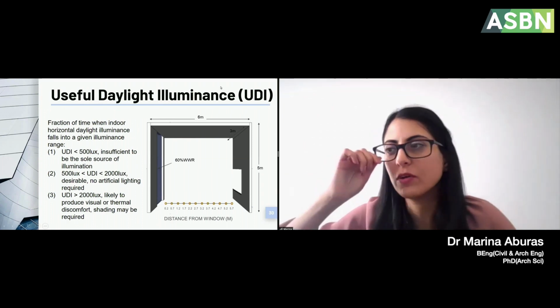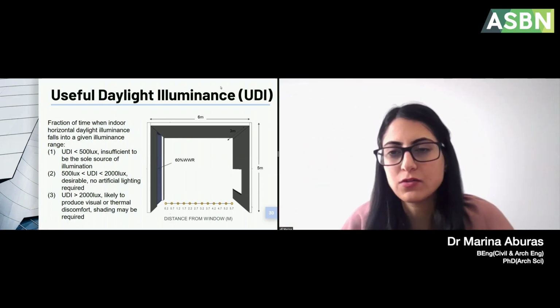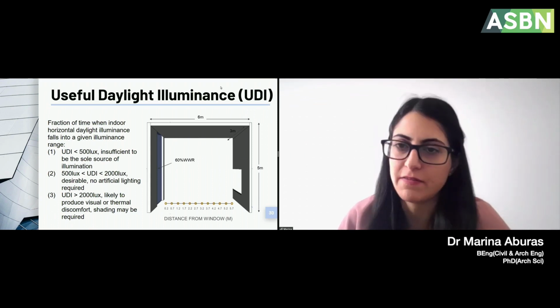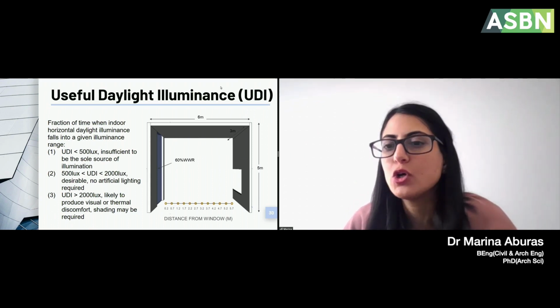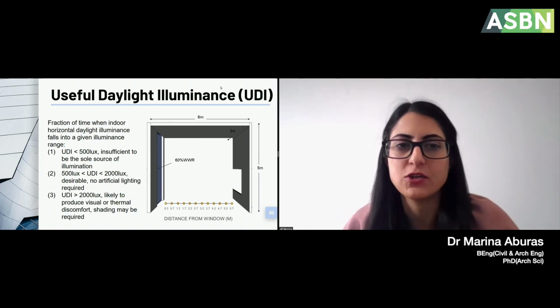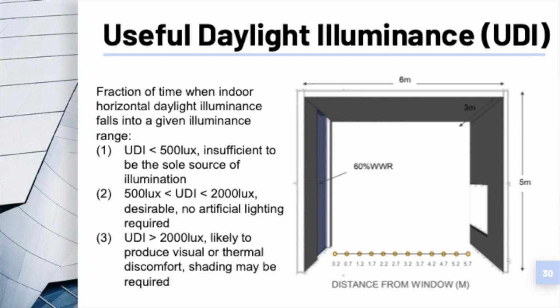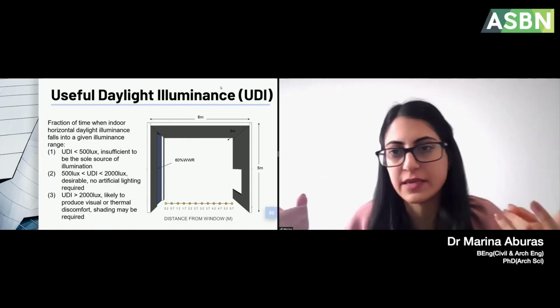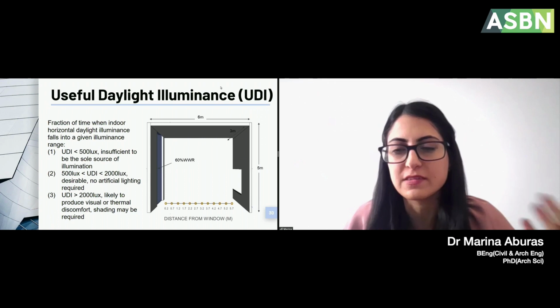And that segued into, now that we've looked at energy, naturally, what about daylighting? So you've got these coatings on these buildings, and they will have an effect on the visual comfort or discomfort of occupants. So the way we chose to look at this was to use a metric called useful daylight illuminance, where we categorize the fraction of time that indoor light on a horizontal surface at the height of a working desk is given in different ranges. So if it was below 500 lux, it was deemed insufficient to be the sole source of illumination. 500 to 2000 was deemed desirable, and greater than 2000 was providing discomfort. These numbers actually represent a worst case scenario where you can have lower levels of daylighting, occupants still be comfortable.